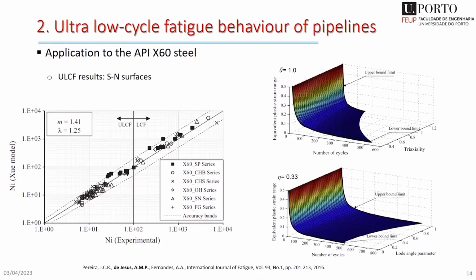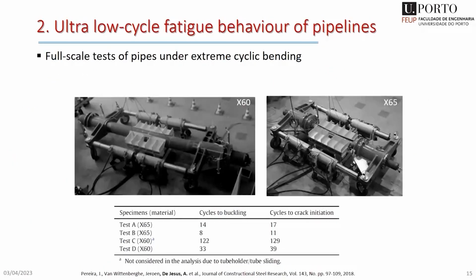Now we must go to the, let's say, the components. So in this project, we had the opportunity with other partners, in this case, ArcelorMittal, to run some large tests on pipes. So we tested two kinds of piping components, straight pipes and also elbows. Here, I will just show you the straight pipes, which were cyclically bent, in order to get a very small number of cycles to failure in the regime that we call ultra low cycle fatigue, which is below 100 cycles, more or less.